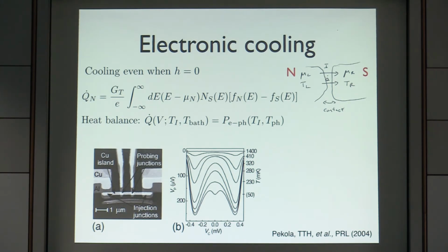Actually, you get cooling even when there is no exchange field, no ferromagnetism anywhere. This was studied especially by Jukka Pekola, starting in the 90s, in so-called NIS contacts, or here an SINIS system, where you study the cooling power of a normal metal resulting from voltage bias across the system. And what one finds is that the electrons on this island can be cooled quite a lot. Typically you might start from a couple of hundred millikelvin, and you may cool the electron temperature by a fraction of 2 or even more.